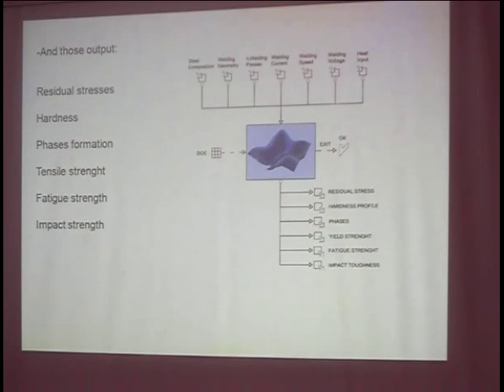We measure the residual stresses through X-rays, hardness profile, phase formation, always through X-rays measurements, and sometimes, where the data was not so clear, with microstructural observation through optical microscopy, tensile strength, fatigue strength, and impact strength, all at room temperature. In this way, in different zones of the weld, depending on the thickness, we measure the residual stress and micro-hardness profile. For example, for bigger welds, we measure in 3 sections the residual stress and the micro-hardness profile, while for thicker welds we measure just in the middle of the weld.